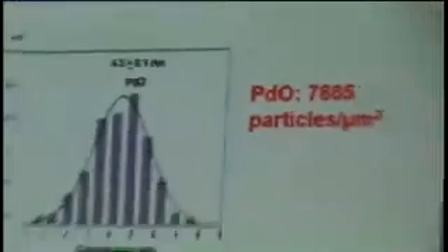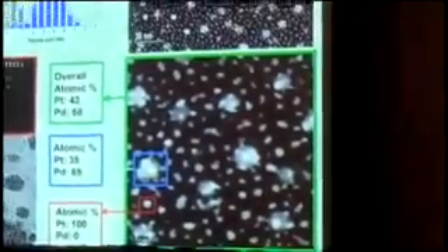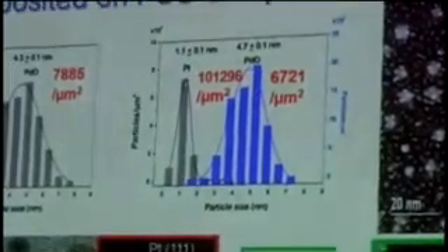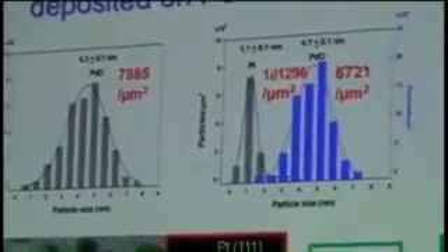So we started with the pre-heat, and we see here about 7,800 particles per square micron. So you can count all the particles. This is what they look like. They're irregular in shape, exactly as we expect, palladium oxide. Now, on top of that, we evaporated some platinum. Now, it's difficult to separate the platinum and palladium, but you can see that the evaporated platinum divided into over 100,000 particles of platinum. And those are the blue specks that you see. So here, you can say, yes, that's platinum, that EDS you can confirm. So we have a physical mixture, but at very short range. Platinum particles next to palladium oxide. Alright?